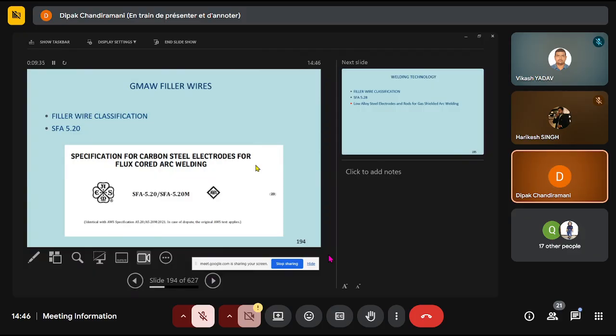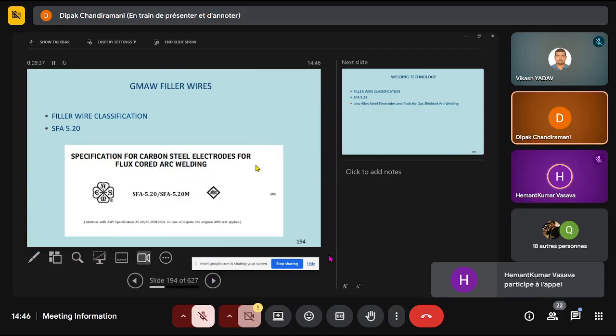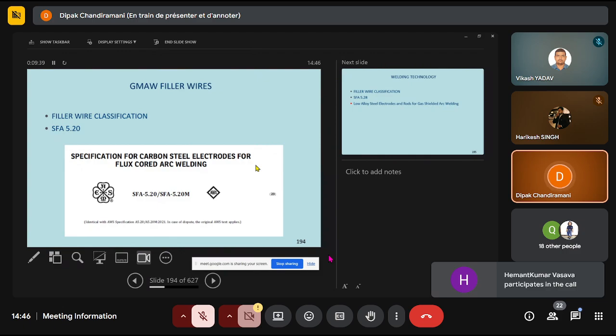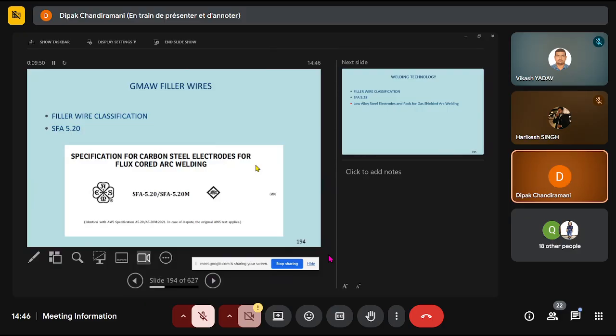Why? One of the reasons in FCAW is that the strip wire which is made into a round tube has a joint. There is no RT, UT, PT, MT done on the joint. So the moment you expose it, it is going to get contaminated and pick up moisture. All these materials are hygroscopic. Once you pick up moisture, you cannot bake. Cannot bake a FCW wire, can you? No. So you have to weld.